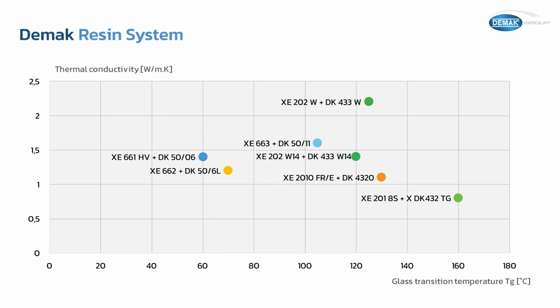In this graph, we summarize the different systems that we have presented, showing the glass transition temperature versus thermal conductivity. We have a quite wide range of systems for the different applications: room temperature curing, heat curing, and also some systems that are in the middle. That means they require only a lower temperature for curing and a shorter time.